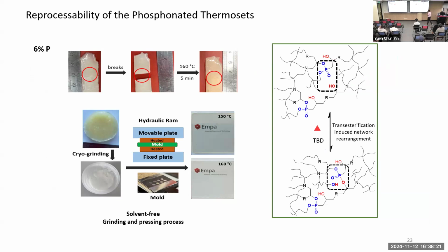Also, the material itself is quite transparent, you can see, and you can powder it and press it back again as well. So you can actually recover the whole polymer back and forth. And this is because there is this covalent adaptable network from the phosphorus chemistry, which we have incorporated into the resin, I would say.